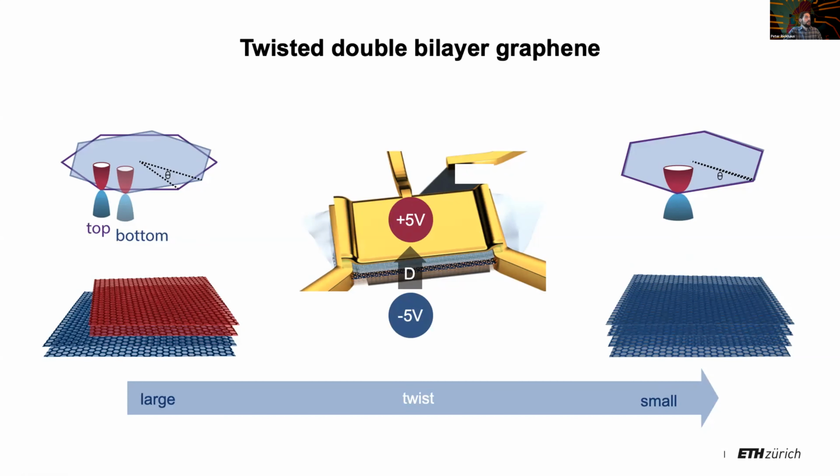And this is what we see here. You can also see that if you follow this line, then it seems that some gap gets closed. And in fact, this is the gap in the bottom layer if we counteract this internal crystal field. The other thing I want to put my fingers on here is that in the middle, we're in a regime where we have holes in the top layer and electrons in the bottom layer, right? So that's between these two zero density lines. But the conductance remains high in this case, as one would expect by just looking at this single particle band structure.